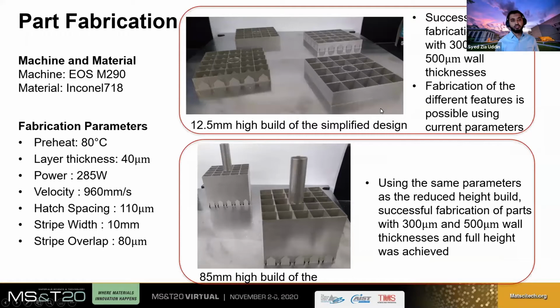So we used, as we mentioned earlier, EOS M290 for fabrication of these parts. And the material that was used is Inconel 718. This material is the same material that is also used for conventional spacer grid fabrication, in addition to a couple of other materials. But this is definitely one of the materials that is frequently used in spacer grid fabrication. And the fabrication parameters that were chosen were all the standard Inconel 718 parameters. And we did not make any variation of parameters at this point yet.